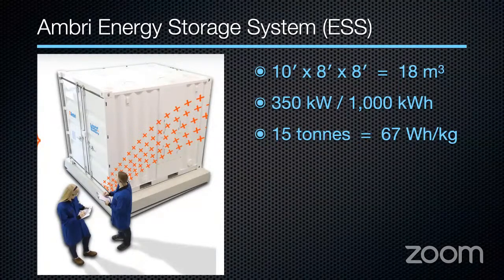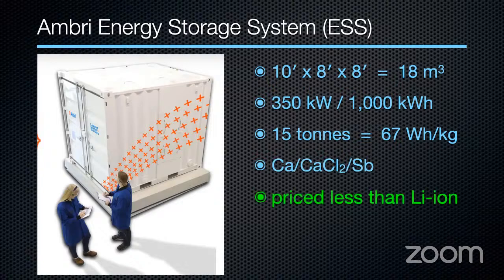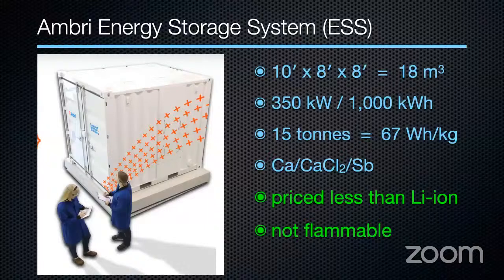And everybody says, oh, that's a lot lower than lithium ion. It's a stupid metric. For stationary storage, you never talk about watt hours per kilogram. There's only one metric that counts: dollars per kilowatt hour per cycle. If I gave you something that had only 40 watt hours per kilogram and had a capital cost of $10 a kilowatt hour, you'd install it. And so right now it's calcium chloride. Calcium chloride, that's the salt we throw on the highways in the winter. That's dirt cheap. And it's priced less than lithium ion and non-flammable. You cannot make this thing burn.